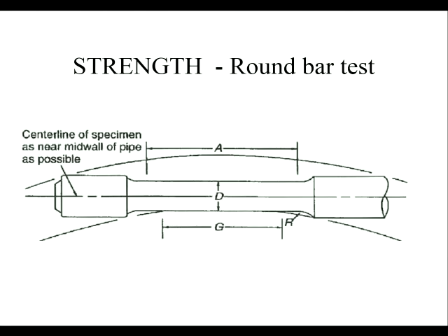So a typical sample might look something like this. Round bar, gets a bit wider, and these bits near the end are used for the gripping mechanisms in the tensile tester, so sometimes they have threads cut in them, sometimes they fit into jaws and pull. The gauge length G, the bit in the middle, where the diameter of the bar is the same, that's the smallest part, so the stress should be concentrated in that area, and the test is valid if the failure occurs in that middle gauge length section.